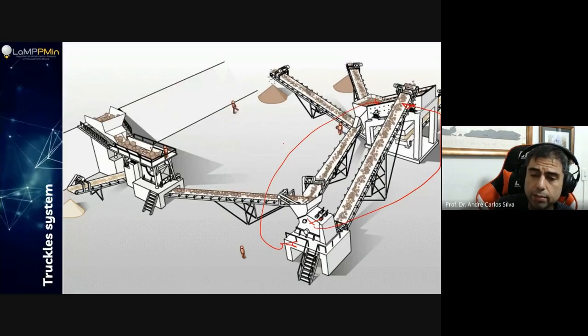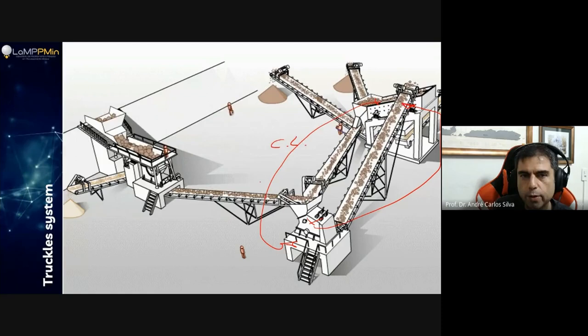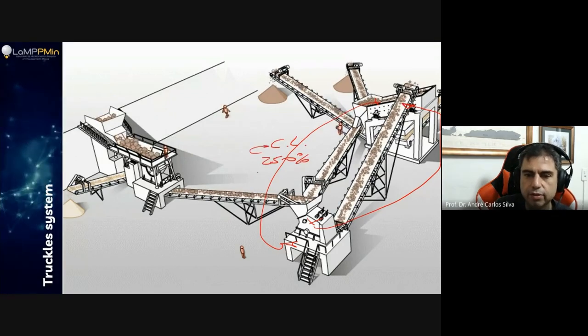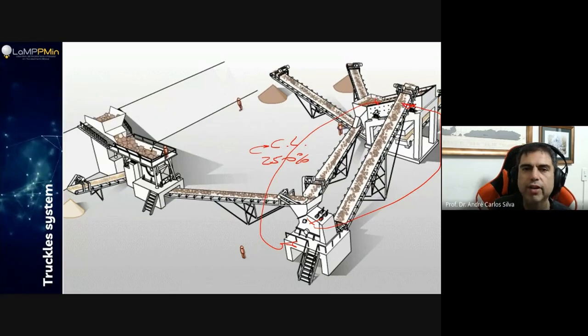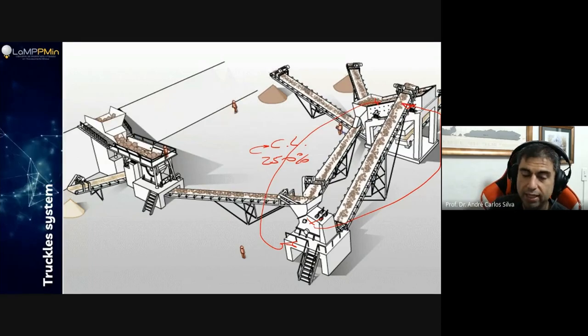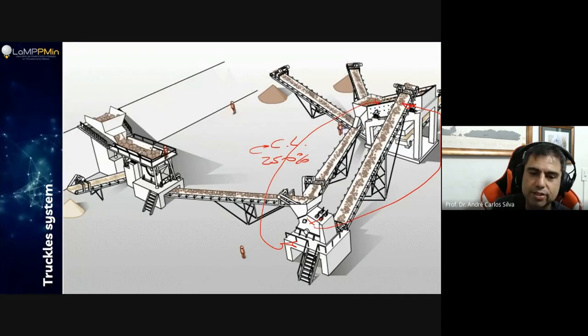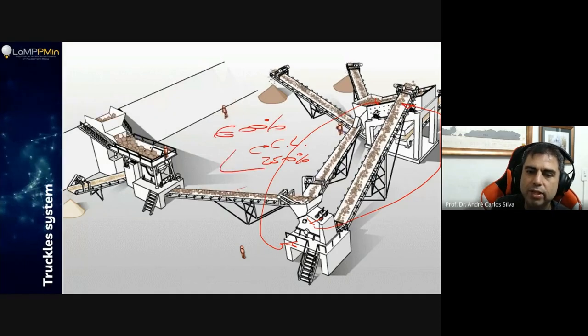And it's quite important for us to evaluate the circulating load, because normally you have something like 250% of circulating load. What this means is, if I'm going to feed new material, 1 ton of new feed, I'm going to have 2.5 tons coming back to the same machine as circulating load. And if you think that this is a lot, just consider this. In Catalão, in our two phosphate companies, our circulating load is around 600% and not only 250.